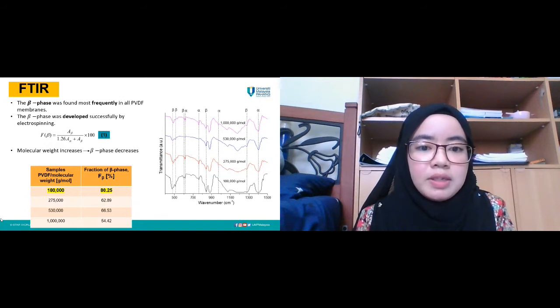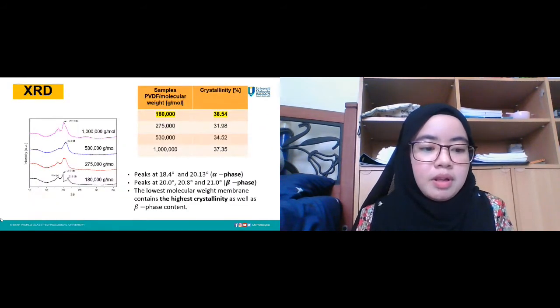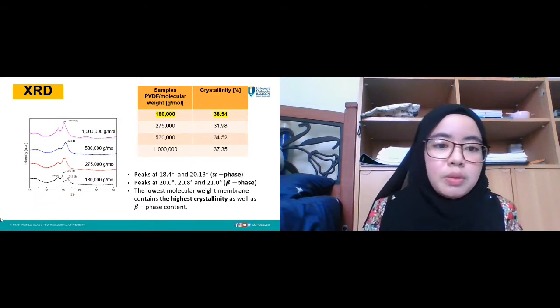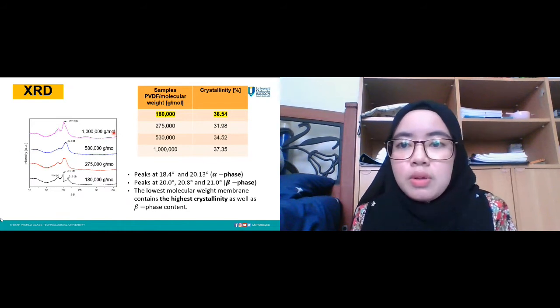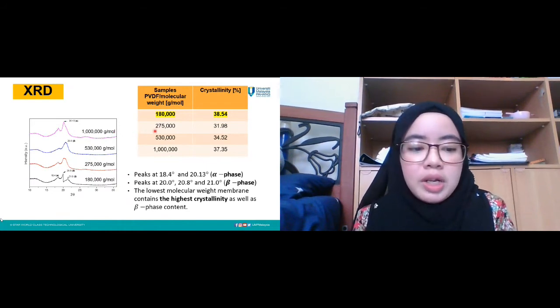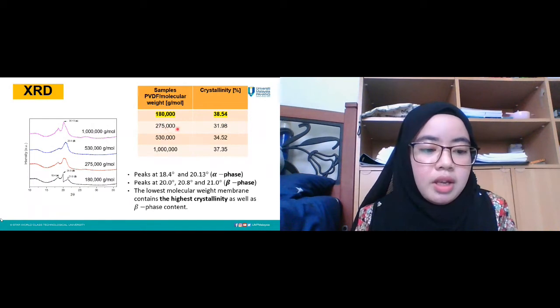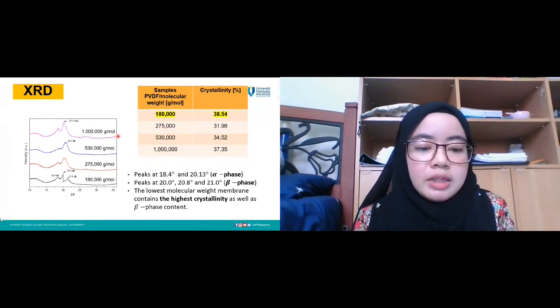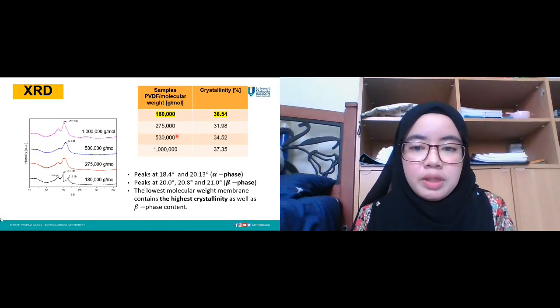The highest beta phase is 80.25%, belonging to the sample PVDF with molecular weight 180,000 grams per mole. Third, the XRD spectra. The lowest molecular weight shows three peaks of beta phase, and it also has the highest crystallinity compared to other molecular weights. So we can say that the crystallinity is related to the beta phase content, because the lowest molecular weight contains the higher crystallinity as well as beta phase content.